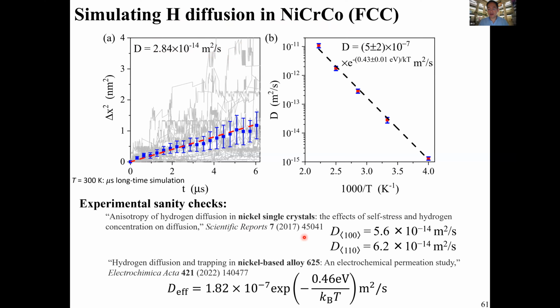However, we do have experimental result for nickel single crystal. So same structure, FCC, but pure nickel, which is 5.6 times 10 to the minus 14 meters squared per second in the 100 direction for nickel single crystals.